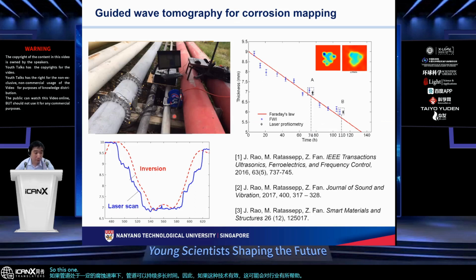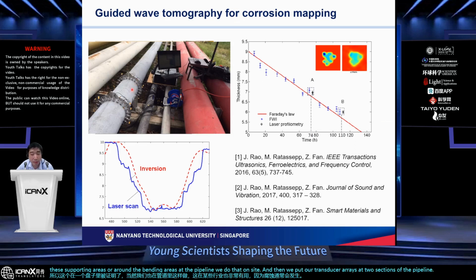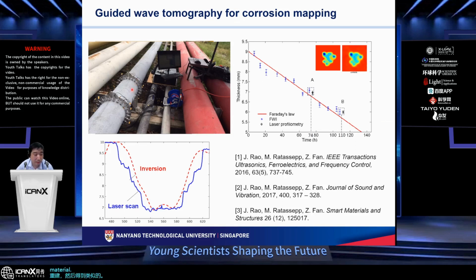So this one was demonstrated in a plate, but of course we also do that in the pipeline, which is also very useful in certain industries because corrosion typically happens at these supporting areas or around the bending areas of the pipeline. We do that on site, and then we put our transducer arrays at two sections of the pipeline and do reconstructions to get similar material loss, or thickness loss, at this hotspot. Okay, so this is one of the first methods that we show that ultrasound will carry information and can be used to reconstruct the thickness map.